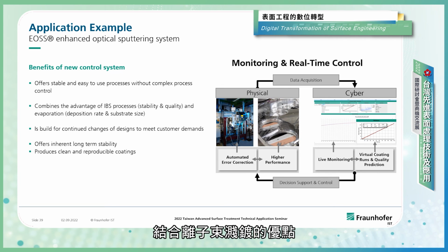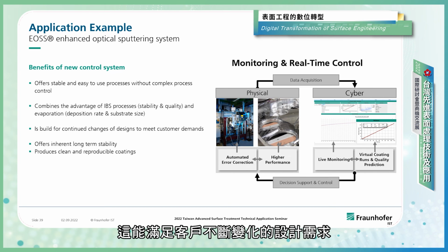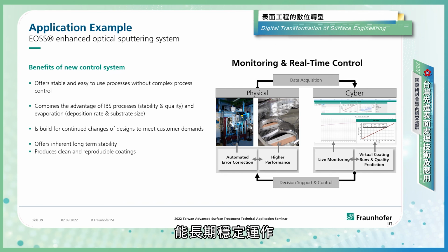It combines the advantage of ion beam sputtering, with its stability and high quality, and evaporation, where you have a high deposition rate, and you can go to larger substrate sizes. It's built for continued change of designs to meet the customer demands, and it offers inherent long-term stability, produces clean and reproducible coatings, and that's a commercial system available now on the market.